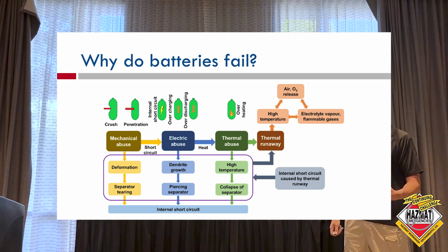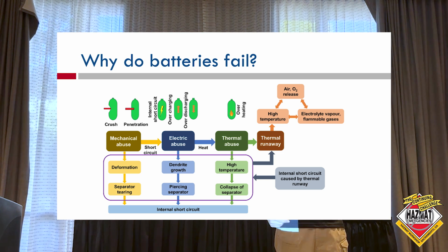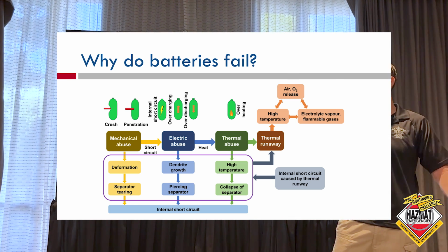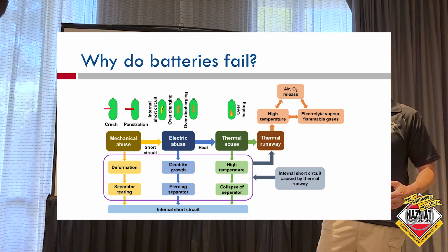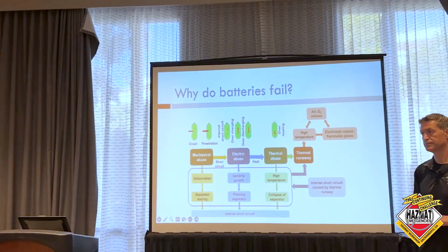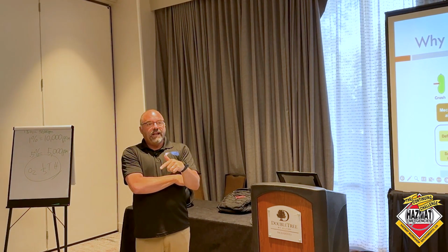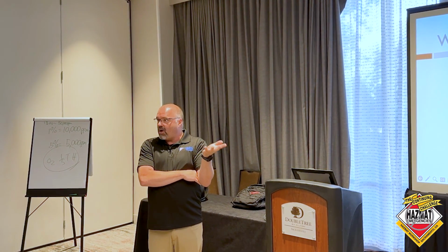Electrical abuse. Electrical abuse is the most common way that we're seeing the e-bikes catching fire. That's some of the stuff that Bobby talked about. Is it getting the right amount of juice? Are you plugging a dozen strips on top of strips, and now you're not really getting the full voltage that you should be getting? And you'll see, tell me if you've seen this, the contractor that's putting together a deck, driving 6-inch screws all day, and he has his DeWalt on fire. And yeah, you over-discharged it. It's not designed for that.